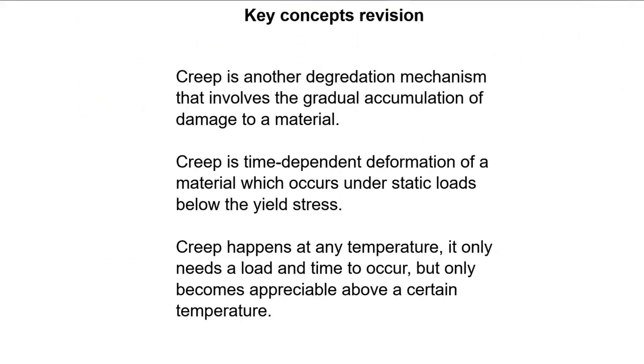So, to review, creep is a time-dependent deformation of a material, and it may occur under static loads which are well below the yield stress. We have looked at how creep is aggravated by both increased temperatures and stresses. The secondary creep regime is where the minimum creep rate occurs. Creep is generally only of concern when the material temperature is above 0.4 of the melting point temperature, or 40%, as dislocation climb relies on diffusion and the presence of vacancies in the lattice. Atoms at the core of a dislocation can move to nearby vacant sites, which effectively allows the dislocation to move by climb.